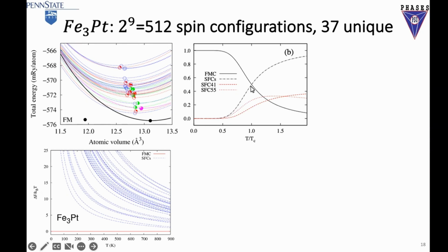It reaches about 50%. So the ground state has low free energy, but it only becomes 50% at a certain temperature. If you increase the temperature further, the ground state becomes less than 20%, even though it's still the stable one from an energy point of view. But the statistical mixing lowers the free energy by increasing the non-ground states, or the metastable states, to over 80%.